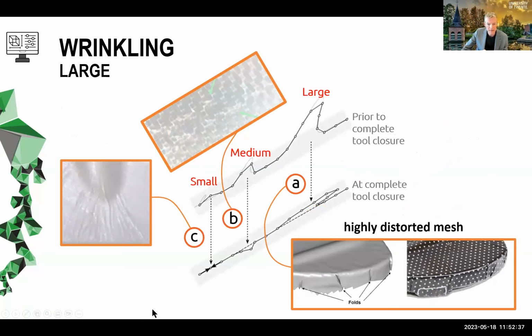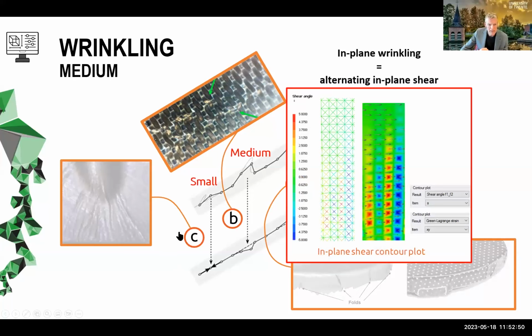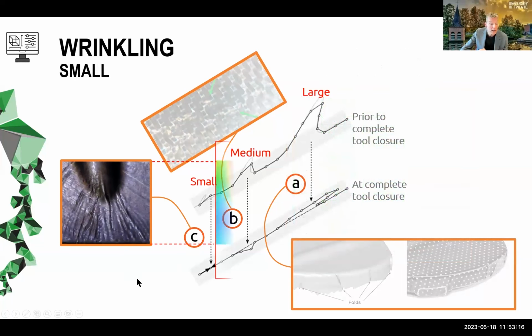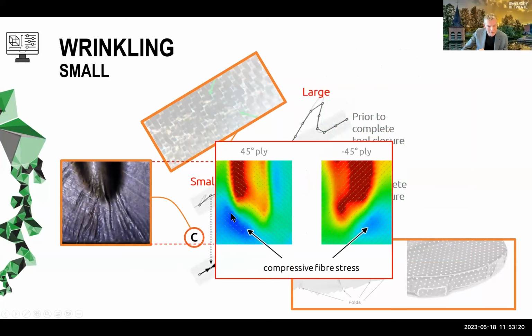We've already seen that these large wrinkles give rise to a highly distorted mesh. These are easily seen in your simulation. The medium ones, if we look at areas like this, and at the shear angle or the accompanying shear stresses, we nicely see this alternating in-plane shear at regions where these kinds of defects are occurring. So these can also be detected just by looking at the simulation data. And the small ones are typically related to the blue colors, negative stresses over here in the different plies. Here we get compressive stresses, and these nicely relate to these micro-buckled regions. So also here, the simulation provides information to predict these kinds of defects.